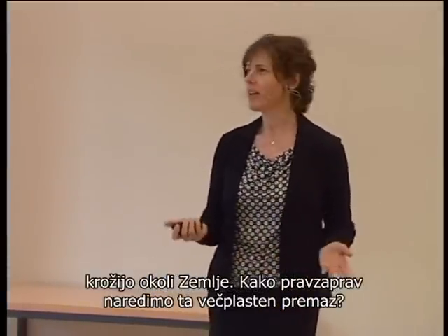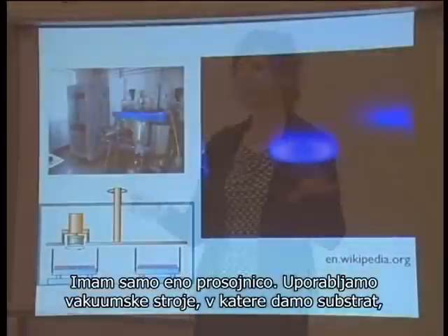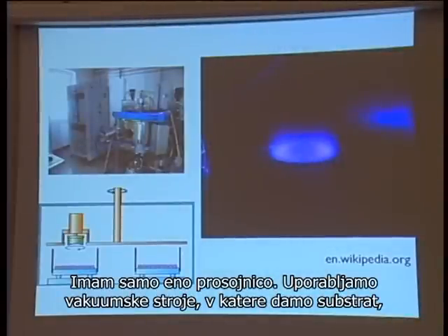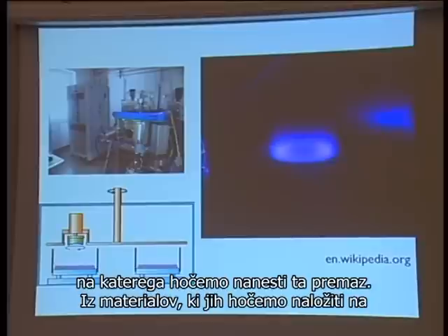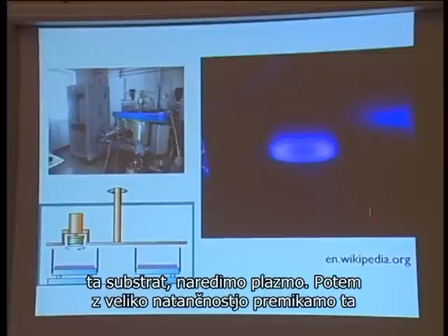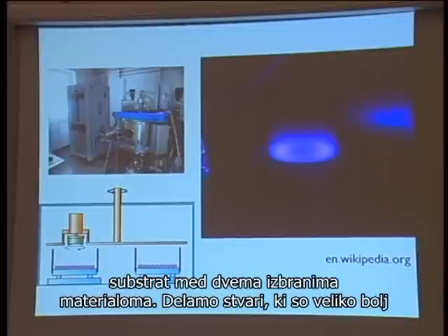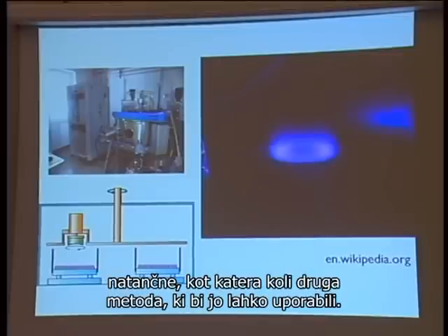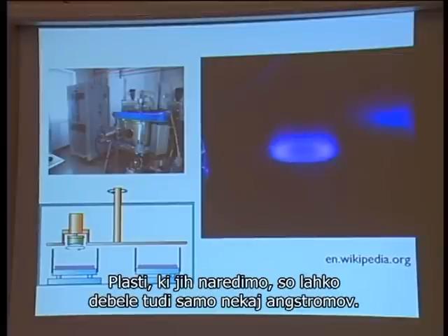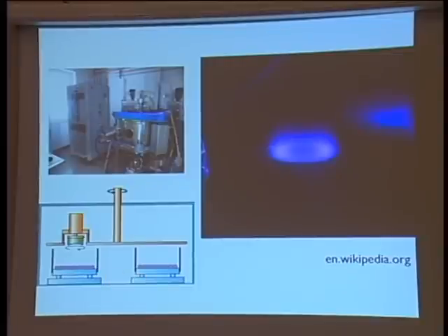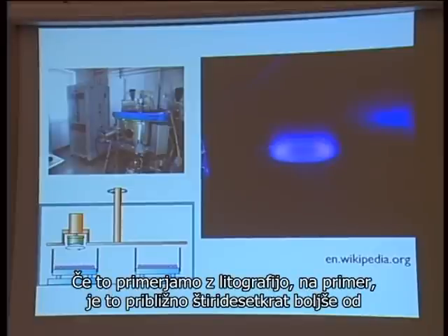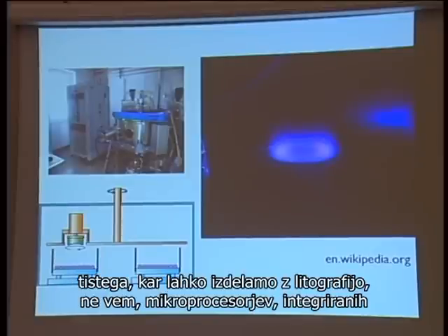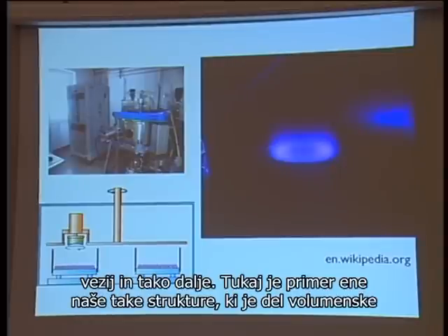So how do we actually make these multilayers? I'm just having one short slide. Just wanted to say we use vacuum machines in which we place the substrate on which we want to deposit this coating. We have inside materials we want to deposit. We form plasma, and then we basically move our substrate between the two materials of choice with very high precision and accuracy. Basically, we can do things that are much more precise than any other method that you can use. So, for example, the layers that we're making can be only several angstrom thin, and as compared to what you can do with lithography, for example, that's a factor of 40 better than what you can do with lithography printing, I don't know, microprocessors or integrated circuits and so on.